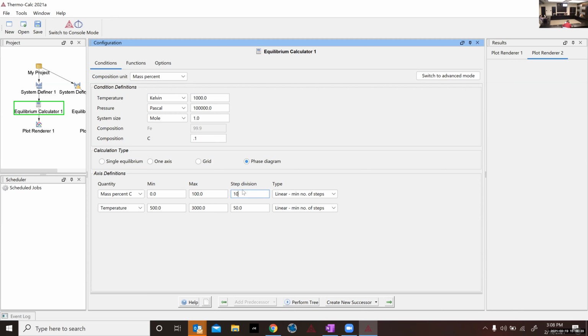I typically use, for composition, a step size of say 1%. If I'm doing a much smaller axis, like from 0 to 0.1% carbon, I would give it a smaller value. But if I'm doing an entire phase diagram from 0 to 100%, I'd give that step size about 1% to start. Temperature, I typically give a step size of 10 degrees.